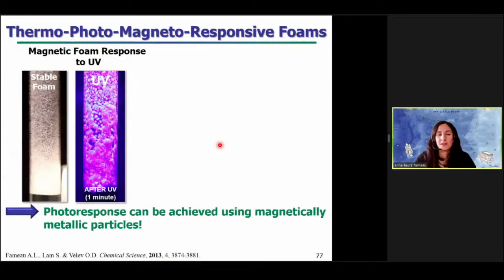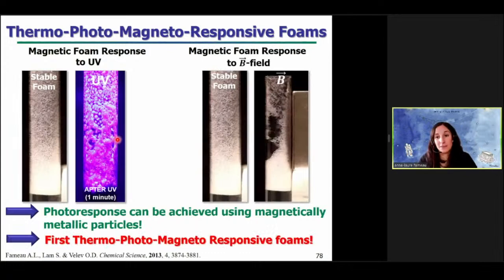Then we decided to use magnetic particles instead of these carbon black particles, because it's also known that magnetic particles are intense absorbers of light irradiation. As you can see here, with magnetic particles, we can also easily destabilize the foam upon UV radiation. But what is nice about using magnetic particles is that you can also destabilize the foam on demand by the application of a magnetic field. As you can see here, we just applied a magnet on the side of the foam, and we can easily destabilize the foam. So by combining this kind of magnetic particles with the fatty acid tubes, we obtain the first thermophotoresponsive foams.